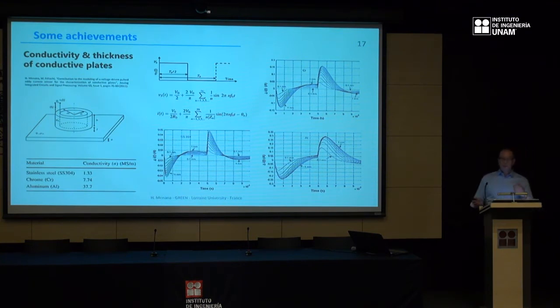For experimental realization, we had problems, we had no material to apply such voltage signals. So we have used Fourier reconstitution of this signal, and we apply alternative sinusoidal sources with different frequencies to reconstitute this signal and the current due to each harmonic. The part of the current due to each harmonic of the voltage: we divide the harmonic of the voltage by the impedance, taking account of the variation of the frequency, and we shift it in time here.